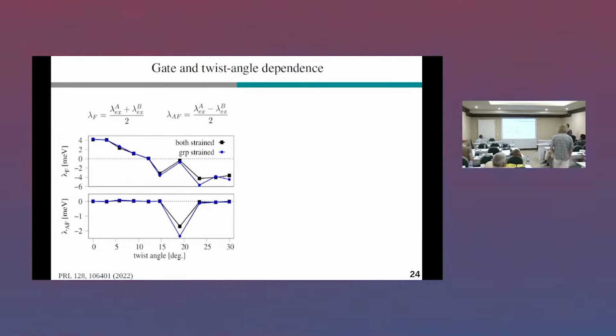However, I have to admit that this antiferromagnetic proximity exchange is not very stable, so it depends very sensitively on the atomic stacking that you employ in your DFT calculations. But still, it's a very nice finding.